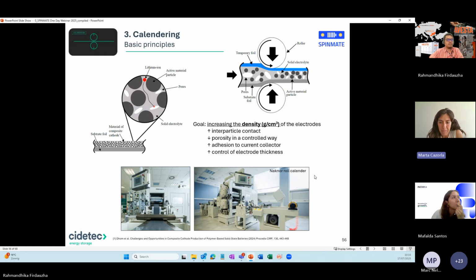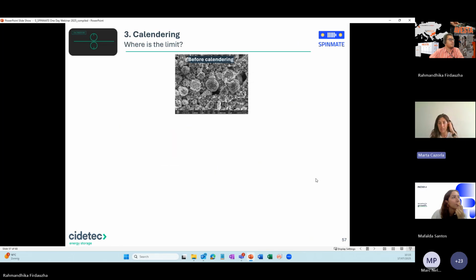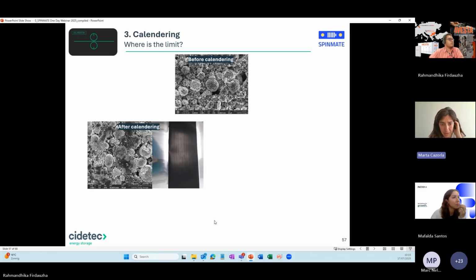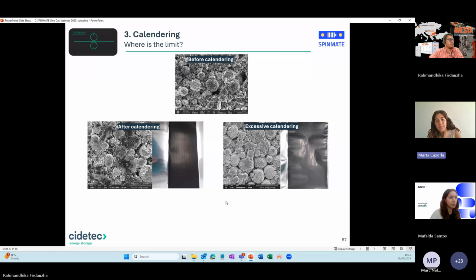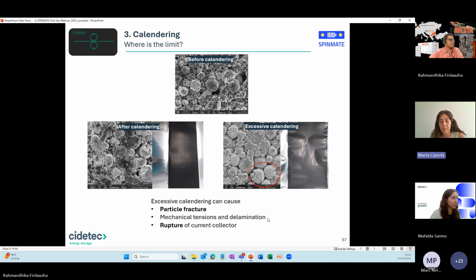So calendaring is important, but it also has a limit. This is a SEM image before calendaring. And then when we calender, we have a smashed distribution of our electrode, in which we have reduced the porosity and we have a more dense electrode, which is something that we want, because we want dense batteries with dense electrodes. But then if we calender too much, we can have cracked particles and also some mechanical tensions in the current collector that can lead to the final rupture. So it's very important to find a limit that gives us a correct performance.